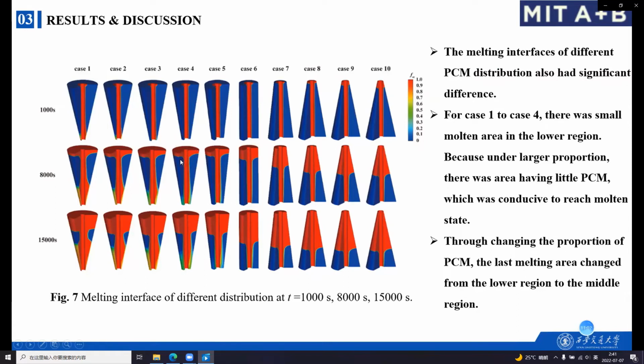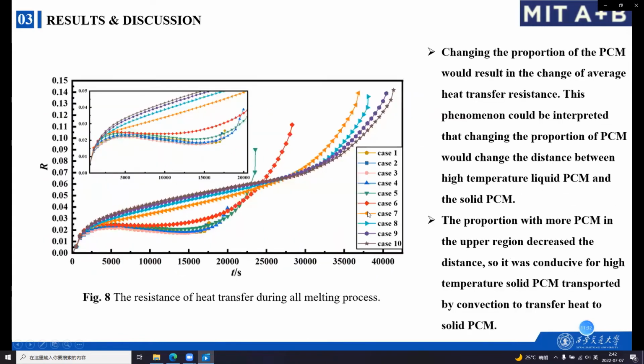Additionally, for case 1 to case 4, at 8000 seconds, the liquid area near the copper tube was large, which was conducive for convection. And through changing the proportion of PCM, the last melting area changed from the lower region to the middle region. What's more, changing the proportion of the PCM would result in the change of average heat transfer resistance.